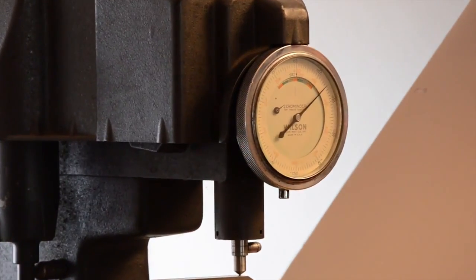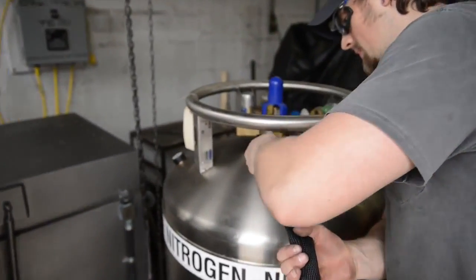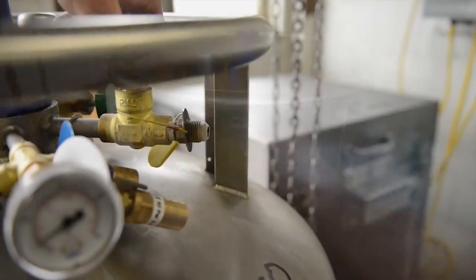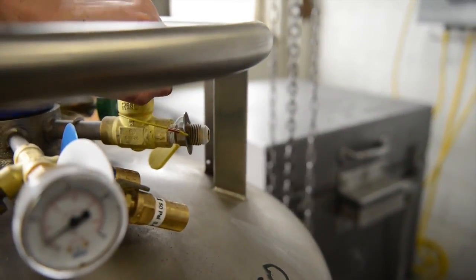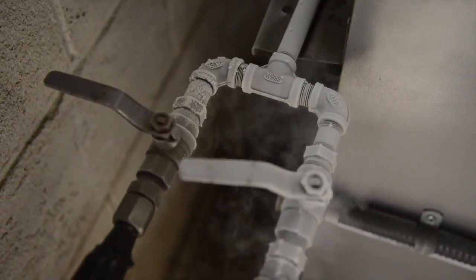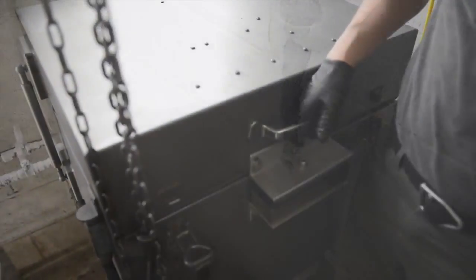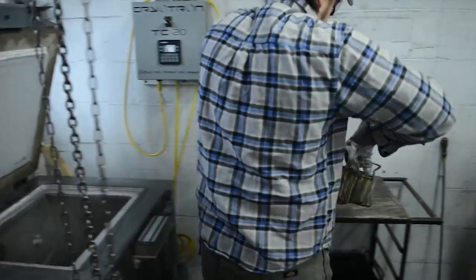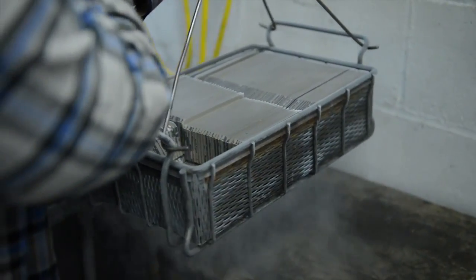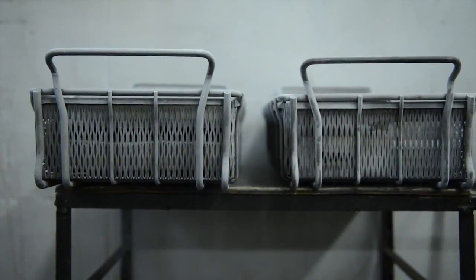We also discovered in our research that A2 steel and some other materials respond well to cryogenic treatment. And cryogenic treatment is when you pour liquid nitrogen in there and get it down to 321 degrees below zero and hold it there for a while and slowly bring it back up to room temperature. What this does with A2 steel, in my opinion, is it kind of perfects the heat treating process.